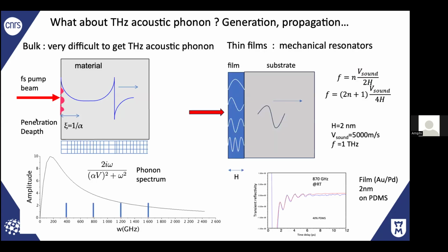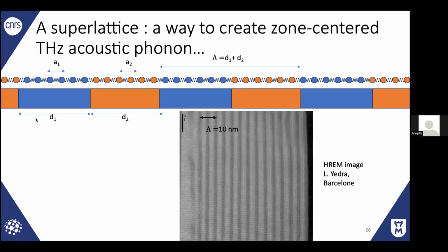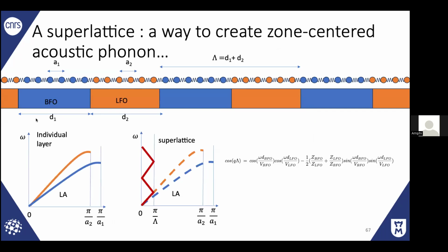Another way is to confine. That's the case where you have a resonator. If you have a resonator, in that case, you can select some frequency in the spectrum you induce by light. So that works. The other way is to use superlattices. As you know, a superlattice is an artificial material made of AB, a superposition of layers. And in that case, instead of having two dispersion curves for acoustic phonons, one for each part, you have an average, a mode folding. So in that case, you can couple light directly with the zone center mode and generate it, because there is different absorption of the light, which is not the same for A and B. So you select perfectly a given frequency, which is usually the zone center one.